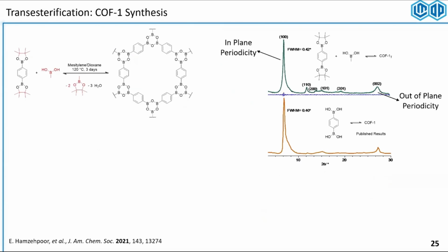So I started doing the same methodology, just adding methyl boronic acid, a little bit of acid or base or no catalyst, and then started having polymers inside my reaction vessels. When we look at the powder X-ray diffraction of these polymers, we found that they have identical phase to the COFs that have been reported with no protection on them. So now we could make COFs from the B-pin derivatives of aryl boronic acids.